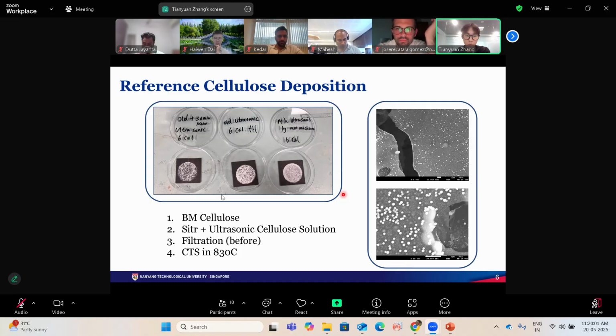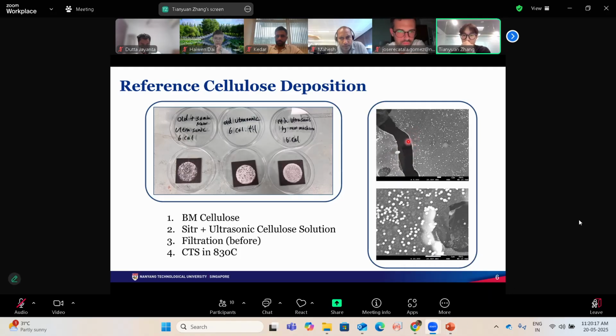And we used filtration for cellulose deposition at first, as the reference paper mentioned. And we found problems very soon, as we can see in the right SEM picture. The copper nanoparticle distribution is not very good, like the number of the copper nanoparticles is very small. And the cellulose sample is bad too.